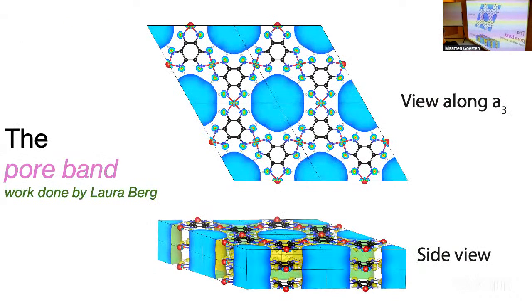So that band is actually electride-like. What we have found is a band which is known to be there for graphite and also boron nitride. This band is called the interlayer band. That is a band which is not localized around nuclei, but in the empty space. With graphite, you find it in between the sheets, a little bit centered in the hexagonal pore. With graphite, this has been experimentally probed to be about 1.1 electron volt below the vacuum level. As I will show you, this one lies much lower in energy.